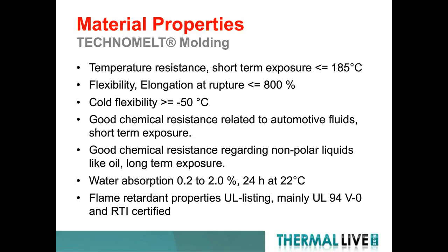Quick general glimpse of the material properties itself. The materials are temperature resistant. For short-term exposure, they go up to about 185 degrees C. Again, the portfolio is tailored to offer solutions across the gamut, but typically we see the maximum short-term temperature exposure to be 185. They're very flexible materials. Their elongation at rupture can be up to 800%, very similar to the plastics you are familiar with. From a cold temperature flexibility standpoint, meaning how well it does at cold temperatures, we can go all the way down to -50 in terms of a mandrel bend or 180-degree bend before cracking.